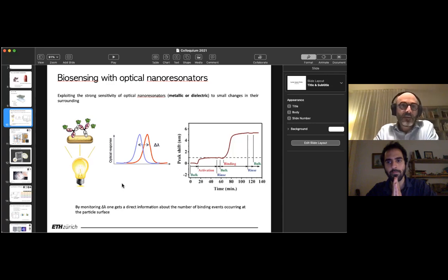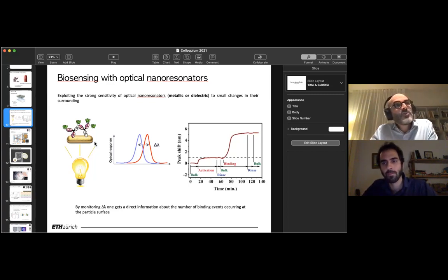These plasmonic nanoparticles are very bad in terms of quality factor, but very good in terms of mode concentration. So under specific circumstances, you're able to achieve that. The only thing is that you may need a full optical table to measure it. You really need to push the measurement to the very extreme. And eventually in practice, it is not always the most important parameter.